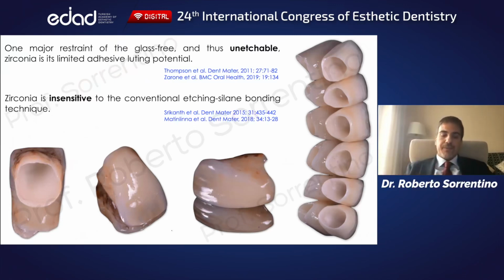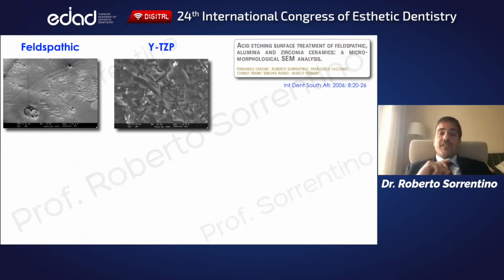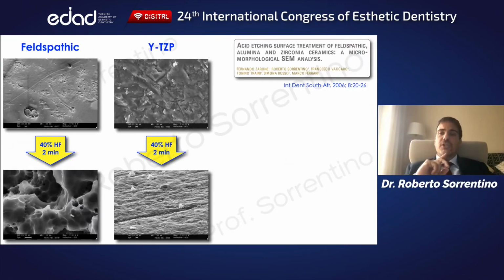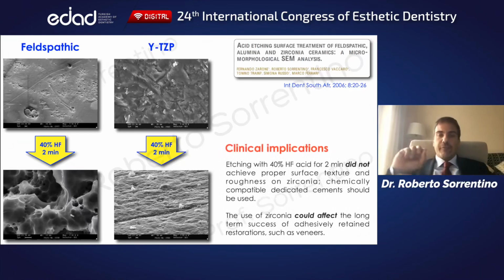A few years ago, we published an SEM study about ceramic conditioning using a very aggressive etching protocol, precisely 40% hydrofluoric acid etching for 2 minutes. We showed significant surface modifications onto feldspathic materials, but not onto zirconia, concluding that to date, the latter cannot be considered a first choice material for purely adhesive restorations, just like veneers and onlays.